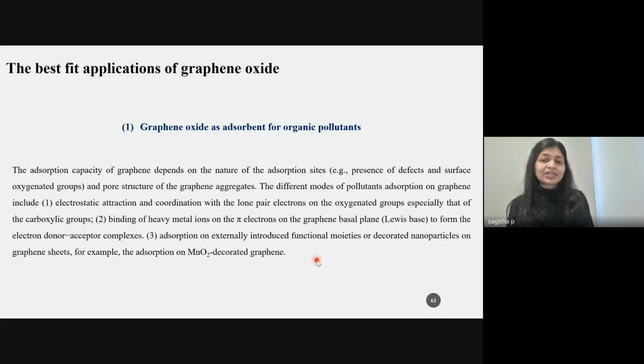Graphene oxide is also used as an adsorbent material for organic pollutant removal. When we compare graphene and graphene oxide, one thing I can say is that graphene oxide has a higher adsorption property than graphene, because graphene, we know, contains only pi electrons. But in graphene oxide, there are polar functional groups as well. These polar functional groups can also interact with the organic pollutant molecules. So pi-pi interaction and also interaction between the polar functional groups are possible in graphene oxide. So graphene oxide shows superior properties in adsorption applications compared to graphene. But in the case of electronic applications, graphene will be more prominent and more used than graphene oxide.